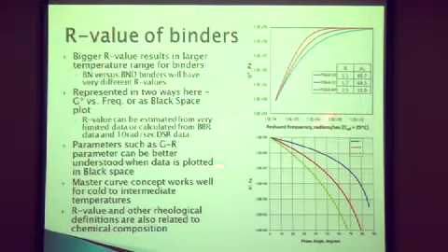What we know here is that, in the plot of G star versus phase angle, the data all of a sudden becomes very important for determining where that cracking will occur. Remember earlier on I showed you the plot of the Glover-Rowe parameter? The Glover-Rowe parameter showed a line in this black space. As the materials age, they start to cross that line. Where you are in the black space is very important, because you have something which is prone to cracking.